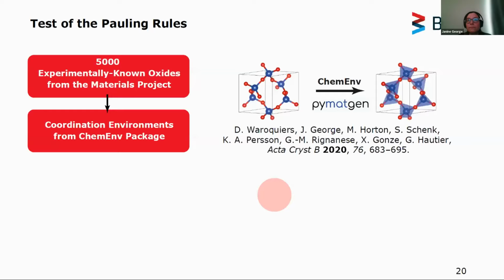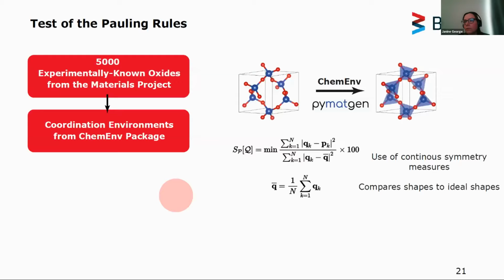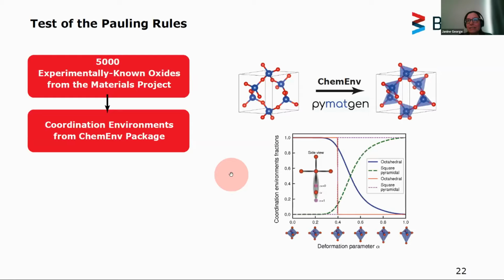So what does ChemEnv do? It uses a so-called continuous symmetry measure. So it compares positions of coordination environments in real crystal structures to ideal shapes. It minimizes the distance by rotating and changing the shape of these polyhedra so that they fit best to the ideal polyhedra, and then evaluates these numbers and can give you the coordination environment for a certain real structure.